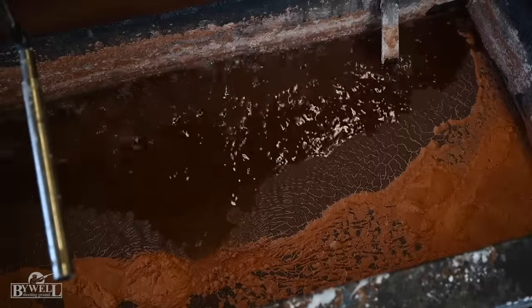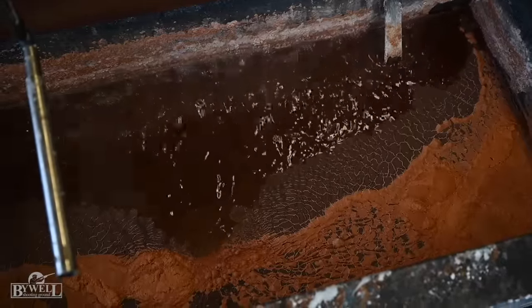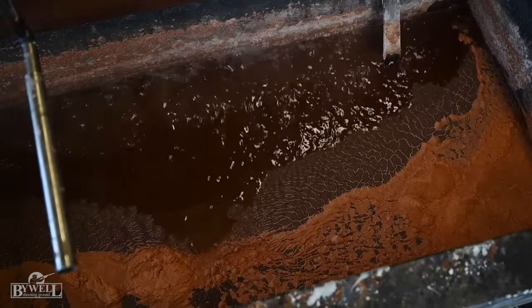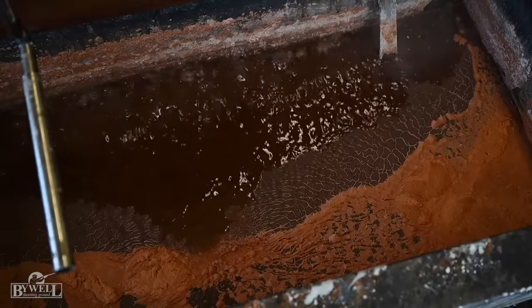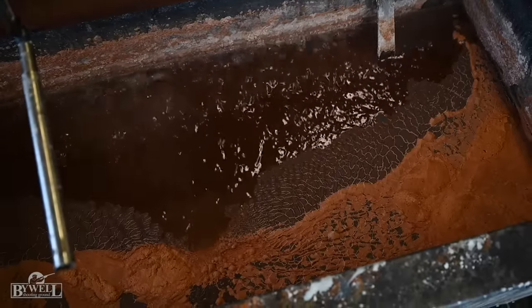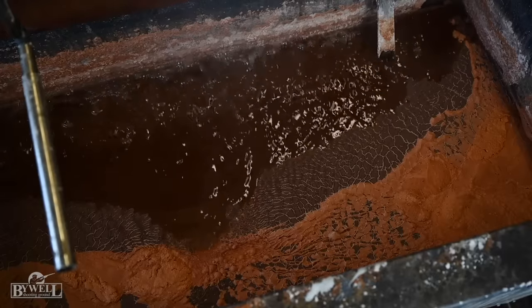And you do your own nickel plating as well? Nickel plating as well, yes. This is a combination plating process that we do here. The beginning is a chemical nickel plating. Well, to tell you the difference: there's electric nickel plating and there's chemical nickel plating. The electro nickel plating has a better quality because it holds onto the material a little bit better. The problem with the electro nickel plating is you will have more material on the corners. So if you have a plate and you put a hole through it, you will have more nickel on the corners of the hole.